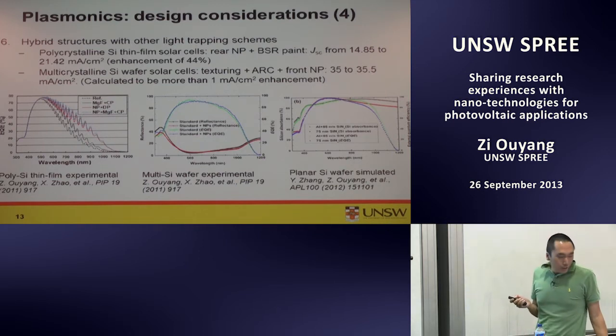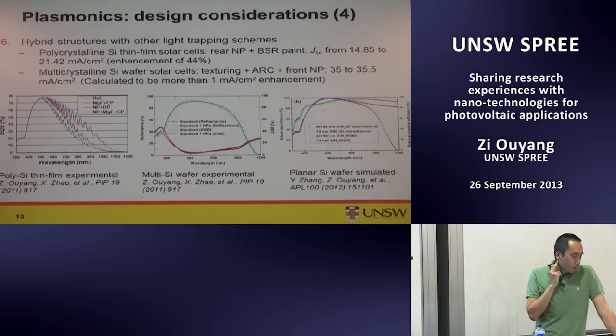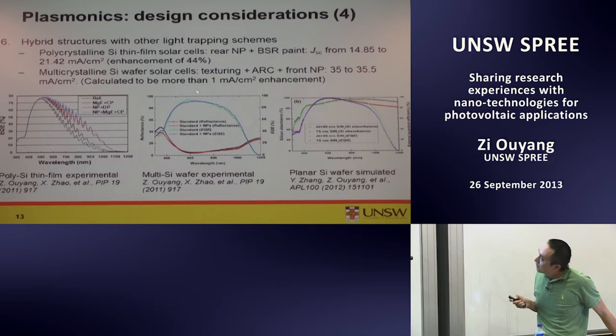And as we can imagine, it's very difficult to get a light trapping enhancement effect on single crystalline solar cells. But for multi-crystalline silicon wafer solar cells, we still have some space to go. So it's very interesting. If you look at it, it's not very clear. The blue one is the one with nanoparticles on top of the silicon nitride, and the green one is without nanoparticles. You actually have a decrease at the peak where you optimize the wavelength for your thickness of silicon nitride, because with silicon nitride on top, you expect almost 100%